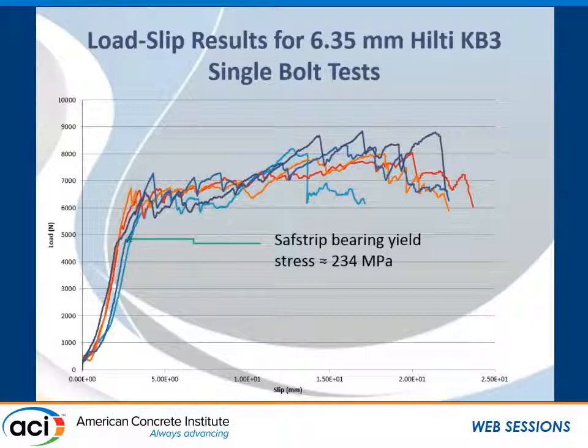The slip test results showed reasonably linear behavior up to what we're identifying as the Safstrip bearing yield stress of 234 megapascals, which would be right around here in the 6.35 millimeter tests. And that was regardless of bolt type, diameter, connection geometry, or concrete strength. Behavior after that bearing yield point, however, was sensitive to the variables I've just mentioned, with fastener type and diameter having the greatest influence on behavior.